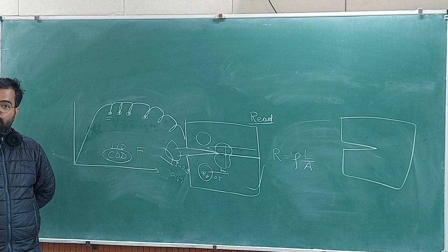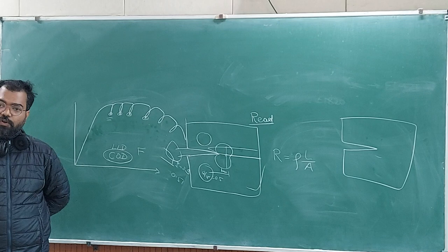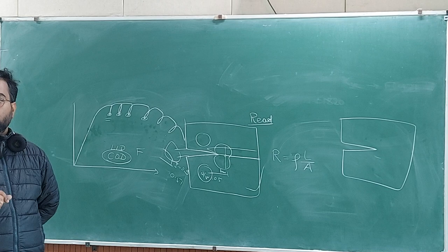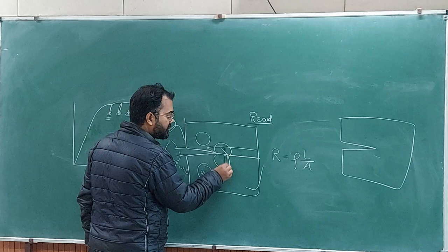So you can measure the change in resistance, and then you have to calibrate this with the crack growth and prove your formula. Theory will give you a formula that if there is this much resistance change, then this much crack growth must have happened. Another problem is there. This crack growth is one value now. At every point, you are getting one value of crack growth.